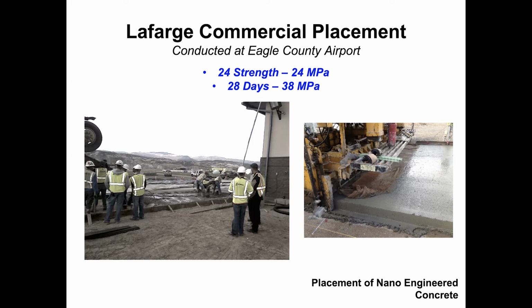Part of that is the way that the colloidal silica creates more of a composite material, so we're getting more out of our aggregate. It's not just the paste. And granted, we are making a kick butt paste, an awesome paste, but we're also locking in that aggregate. So when you start seeing that abrasive wear, you get some, I hate to say work hardening, but at least polishing effects from the aggregate, instead of there being a weak bond between the aggregate and the paste and we're just tearing out aggregate.